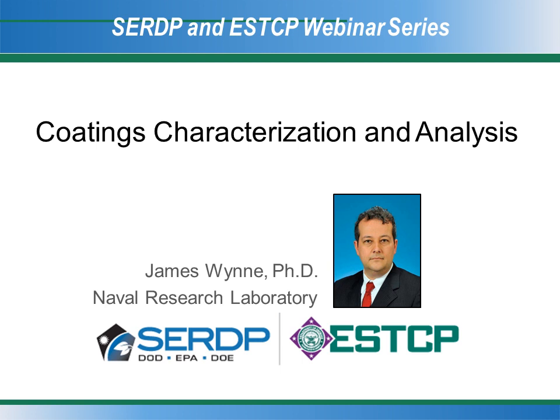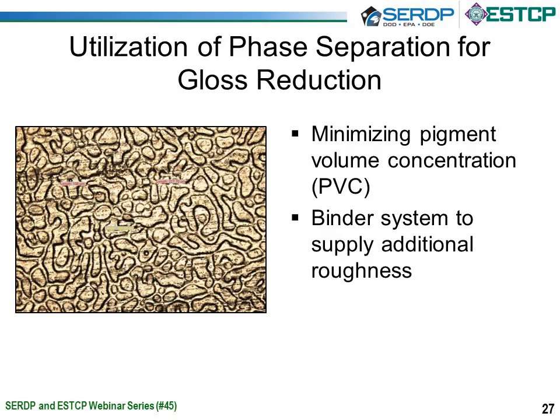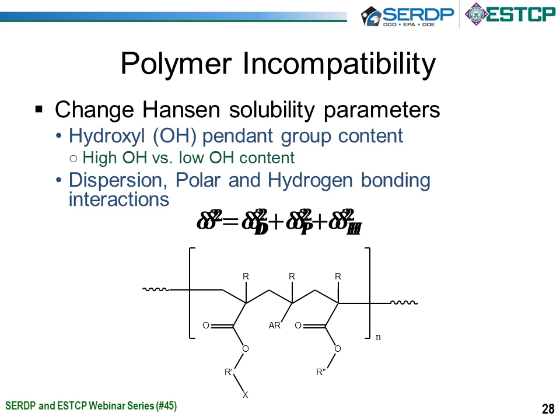Thank you. I'll start on slide number 27 and reiterate some of the things that Mark just said. Knowing that we are extremely limited in the amount of pigments that can be successfully incorporated into a durable powder coating, we were forced to look at other methods of gloss reduction. So in an effort to seek these other methods, our attention turned to the binder system and utilization of the phase separation that polymers would naturally give us if we selected the correct combination. This phase separation ideally would result in additional roughness and give the desired gloss reduction that we wish to achieve for military applications.